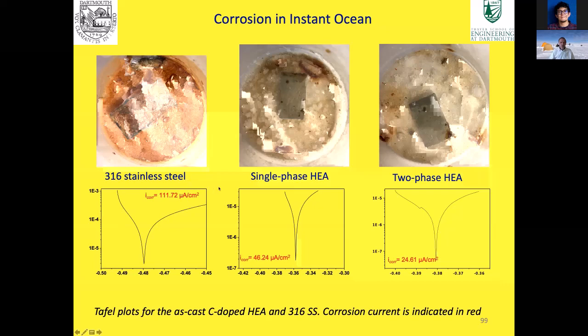We did a little bit more sophisticated study where we looked at the corrosion currents for these different materials, and you can see that the stainless steel has a much higher corrosion current than the single-phase high-entropy alloy, and the two-phase high-entropy alloy is actually better still, so it shows the best corrosion properties of the materials.